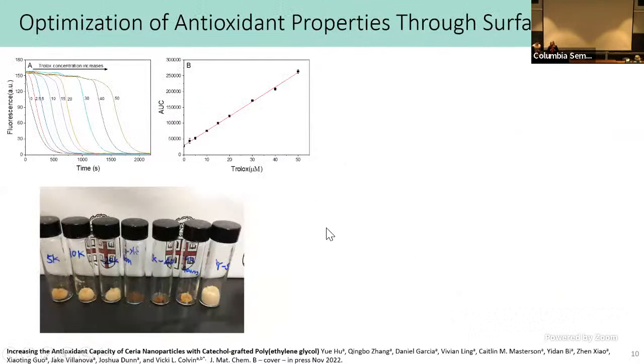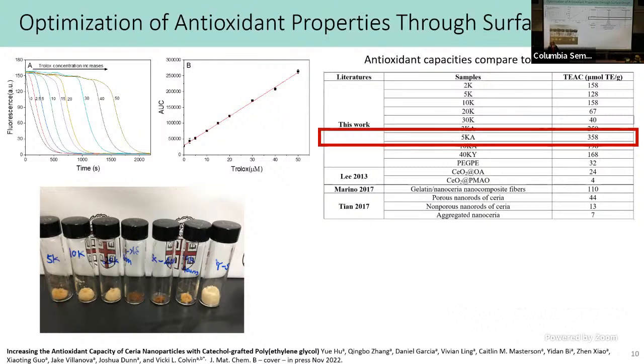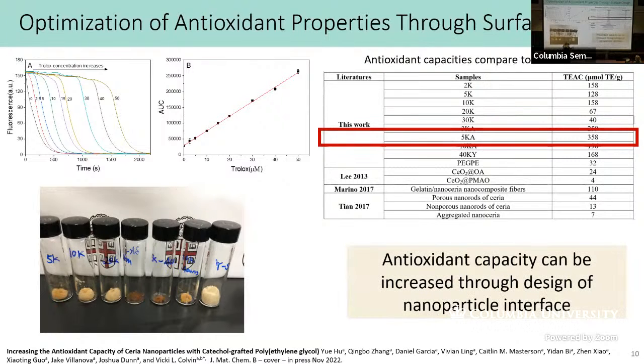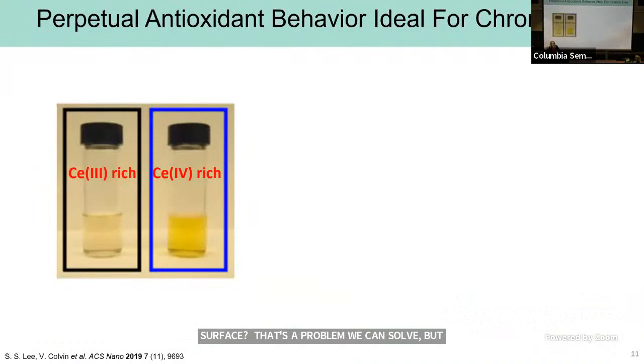There we go. Yay. All right, I'm going to skip this slide, except to say there's some really amazing chemistry that my student Yue Hu did. What's interesting about this material, these are freeze-dried samples of the cerium oxides. They go right into water. They are stabilized by very carefully designed polymers that activate this perpetual antioxidant behavior. So it's an interesting trick. And if you're a materials person, we can talk offline. How do you put a polymer coating on an inorganic system and still allow access to the surface? That is a problem we can solve, but it does require a lot of thought about what those materials might be.